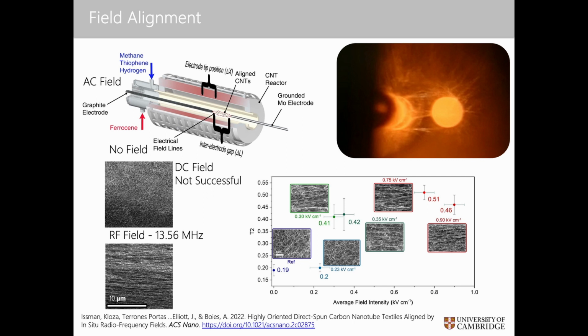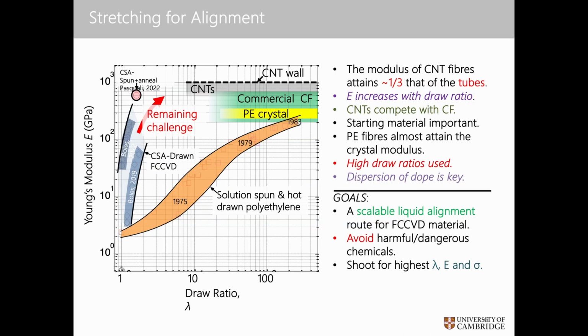So this is another result that we're really excited about. You can think of this y-axis as an orientation parameter, kind of the degree of alignment here, and we get that going up and to the right substantially as we increase our field intensity. But that's not the whole story. We've got a long way to go in this, and I would say a lot of games to play.